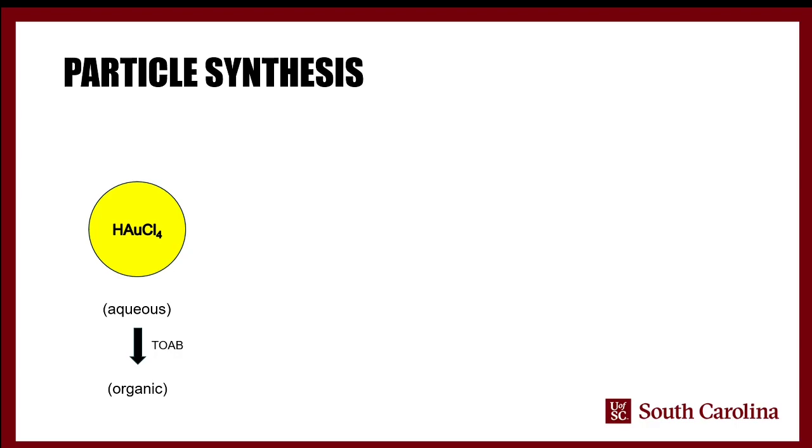But in aqueous solutions, you have a number of ligands available to you that are both small and also very charged, which allows you to synthesize a very stable solution of these nanoparticles. In non-aqueous phase, you're a little bit more limited, because you don't really want to have a charged ligand, because that will lead to agglomeration and crashing out of these particles from solution. And so in my case, I use what's known as the Brust method to take a gold